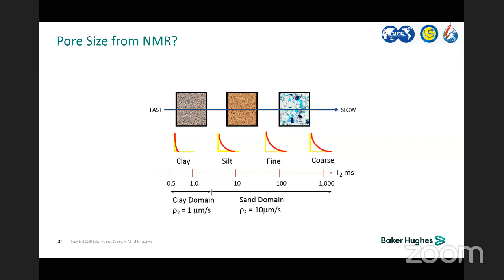But in a water bearing zone, where the NMR depth of investigation is just 4 inches and most of the time is flushed with the drilling fluid mud, we can see that the main variation of the T2 will be dominated by the pore size. If we have a large pore size, it will take a long time, and if we have a small pore size, it will take a short time.